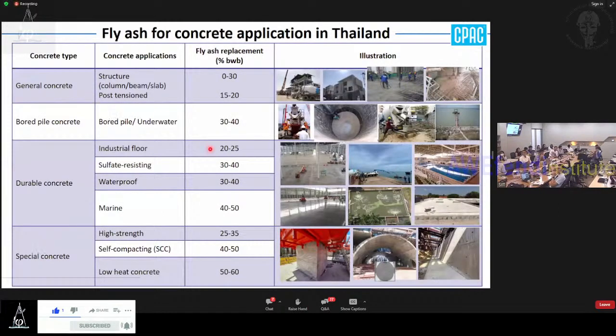I just want to give you some photos of applications in Thailand where we use fly ash for various concrete applications. For the concrete types here, you can see we use it for general cast concrete structures and post tension. You can see the fly ash percent as a replacement of cementitious material, starting from no fly ash up to 30% replacement of the cementitious material. For post tension, as I mentioned, in Thailand we use it for high-rise buildings. So we need some fly ash to give better pumpability of the concrete. And for bored piles, we use fly ash around 30 to 40%, even in underwater concrete work.